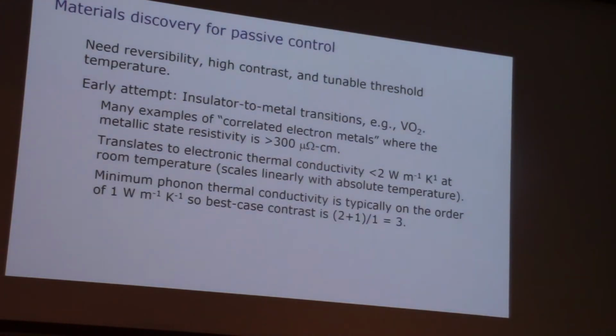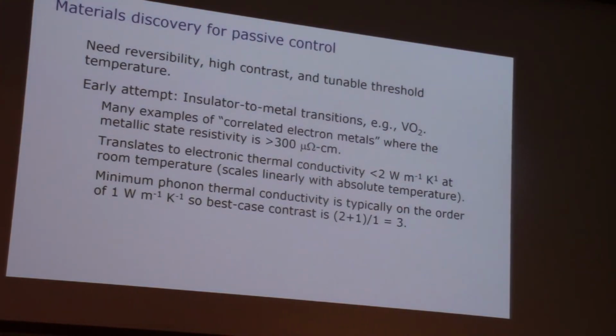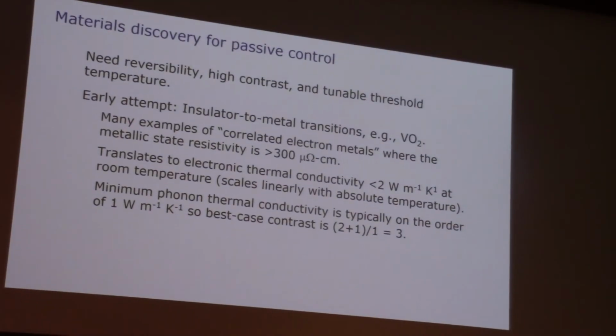All right, where does this go back? So passive control, thermal regulator. I want a material that has a low thermal conductivity and then increases to a higher thermal conductivity. Well, there's a well-known class of materials which are called insulator to metal transition materials. Vanadium dioxide is the most studied, most famous of these materials. It goes from a really good electrical insulator to a metal, but not a very good metal, at a very abrupt temperature around 360 Kelvin or so.